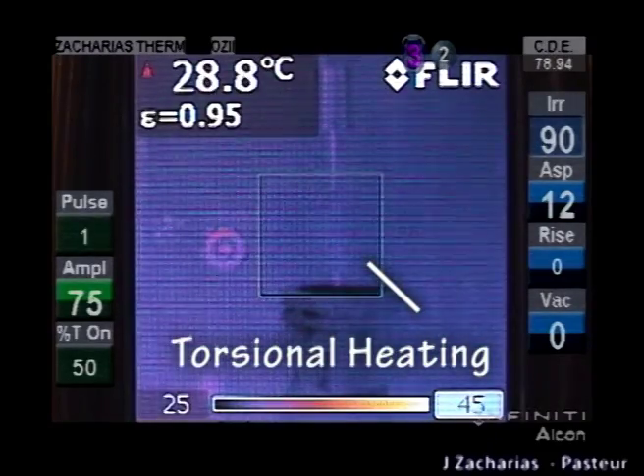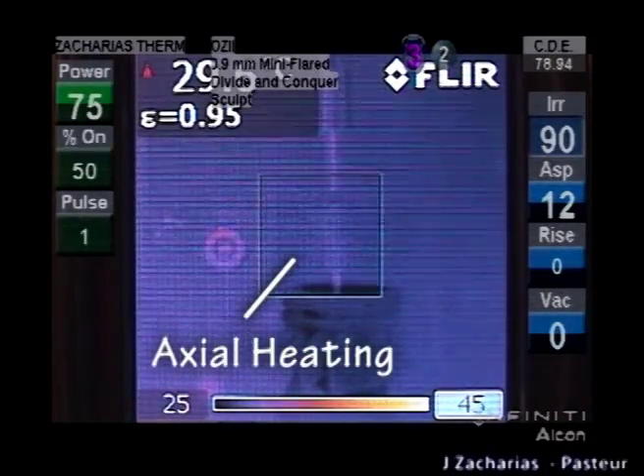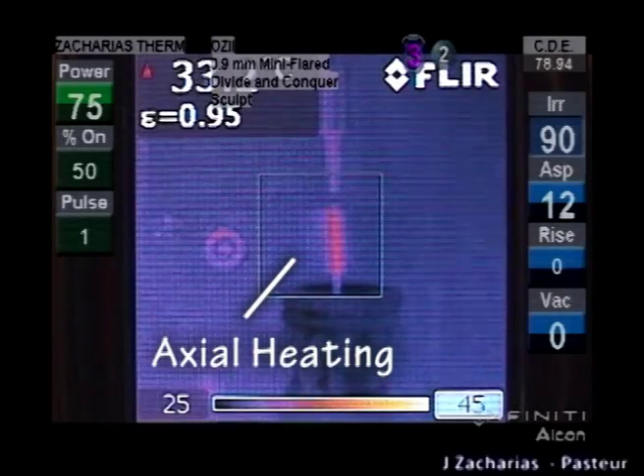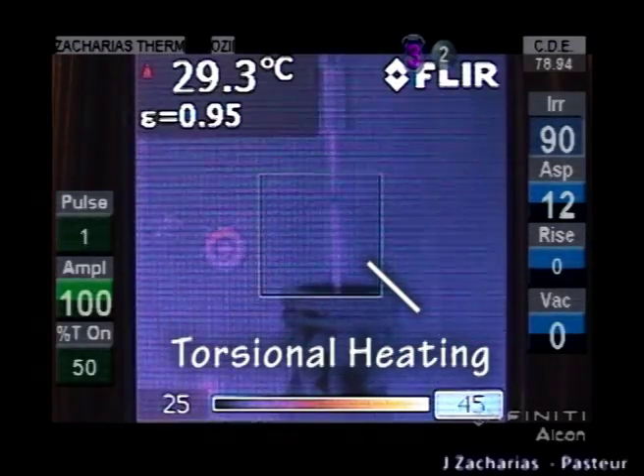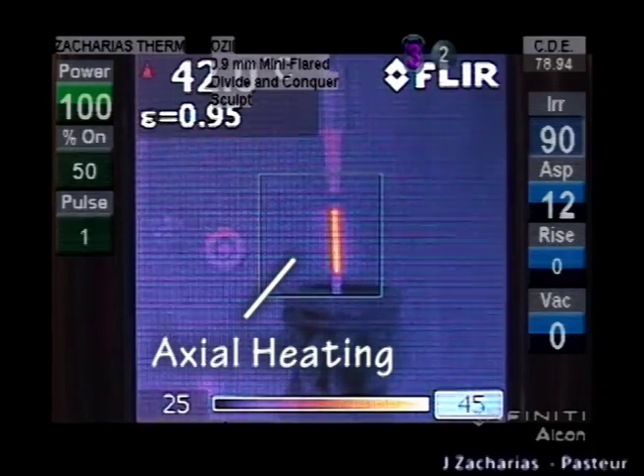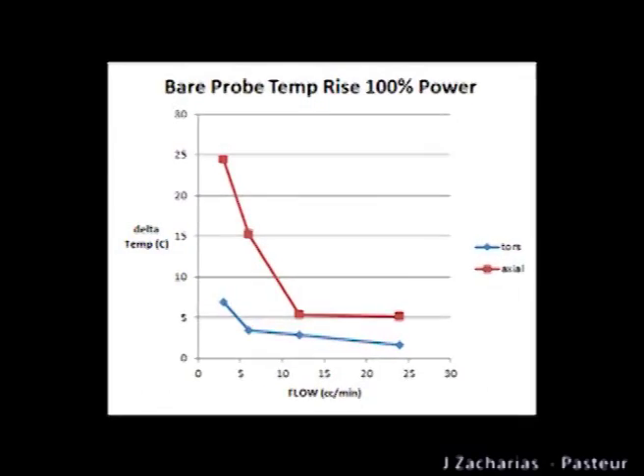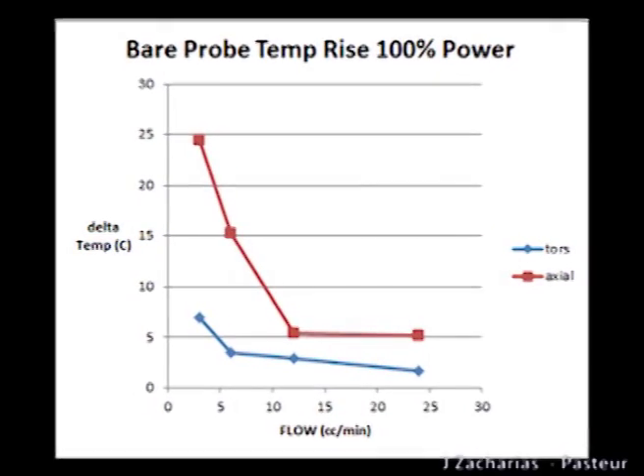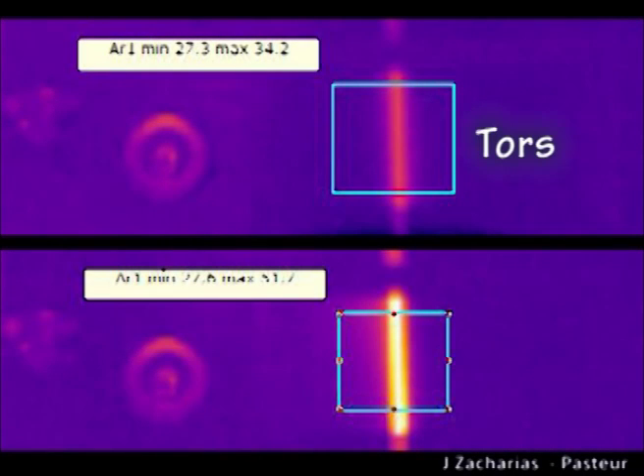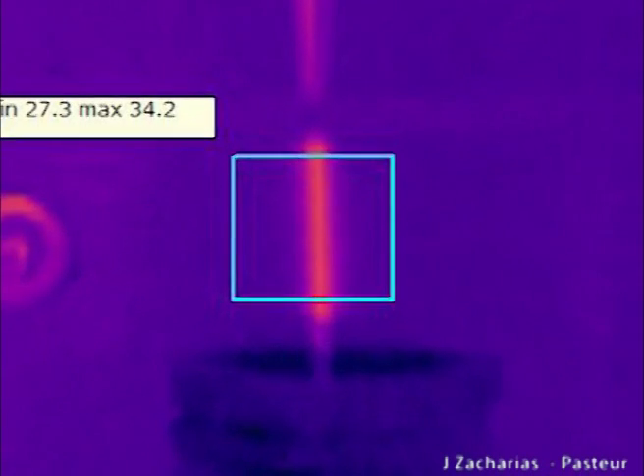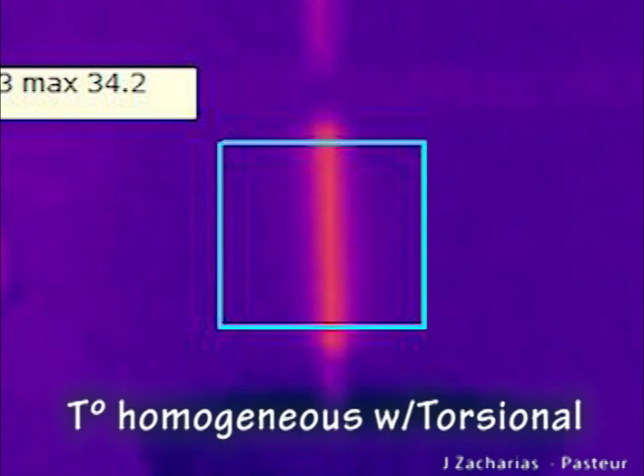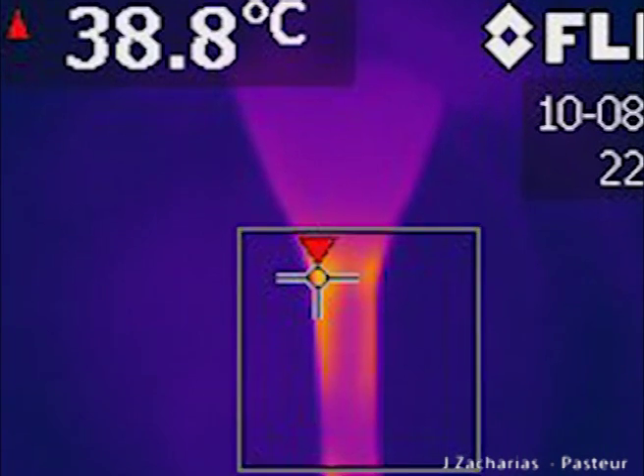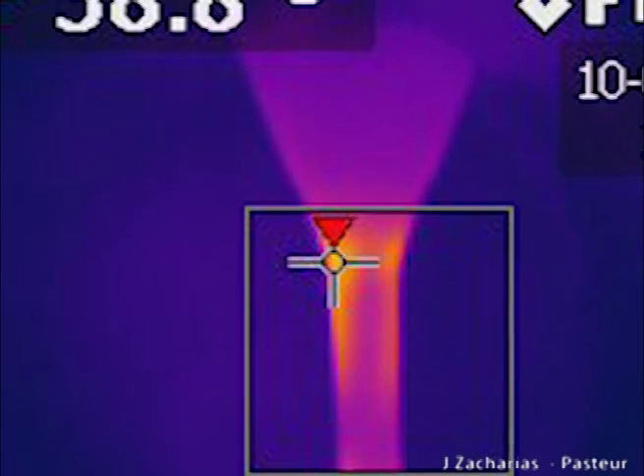Ultrasonic activation of bare probes produced an evenly distributed temperature increase in axial and in torsional modes. We were surprised to find out that torsional activation did not heat up the shaft of the bare phaco probe more than axial. High US power and reduced flow produce more pronounced temperature elevations with axial. In all tests, the probe self-heating phenomenon described was more relevant with axial operation. No focal temperature increase was found in the shaft of the probes that could correlate with the warm zones observed at the back of the sleeve in torsional mode.